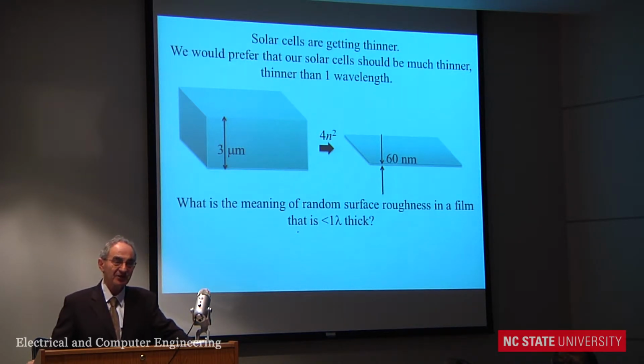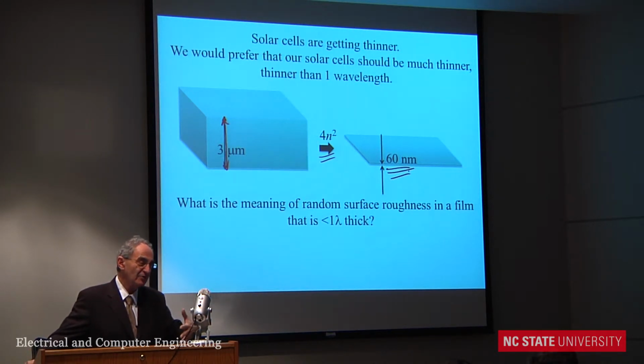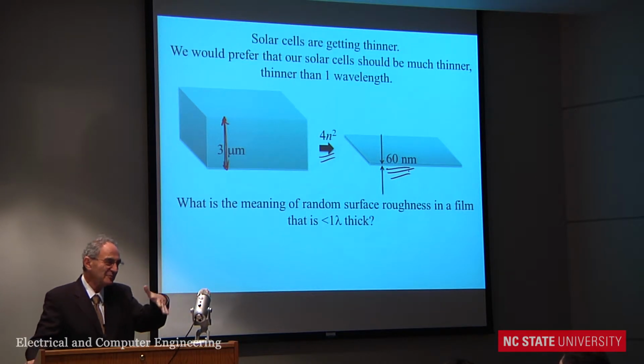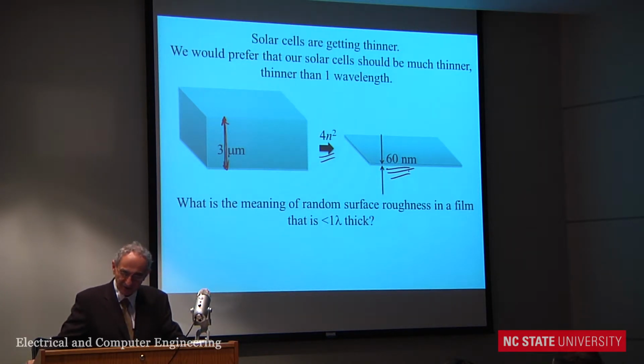Suppose you had a gallium arsenide solar cell, and it's direct band gap, you want to really absorb all the light. You could make it 3 microns thick. Then you'd be 100% sure that you're absorbing every last solar photon available. Now, if you do the texturing, then you pick up the 4n squared factor. Now it's 60 nanometers thick. Now, nobody today talks about making solar cells 60 nanometers thick. But in the future, they will, because we keep making them thinner and thinner. Why shouldn't we go all the way to 60 nanometers? Now, if you're 60 nanometers thick, you're actually thinner than the wavelength of light. Now, what is the meaning of random roughness if you're thinner than the wavelength of light? I don't think the term random roughness means anything if you're thinner than an optical wavelength.